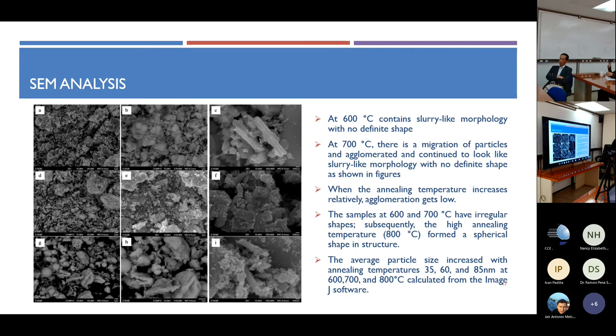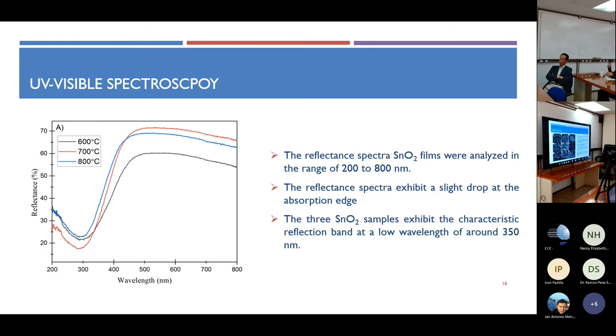At 800 degrees Celsius, it forms a regular, spherical shape. We can still see agglomeration and migration, but compared to the above sample, it is very much less. The average particle size increases with annealing temperature: 35, 60, and 85 nanometers for 600, 700, and 800 degrees Celsius.